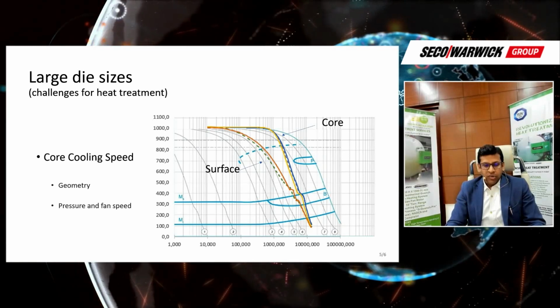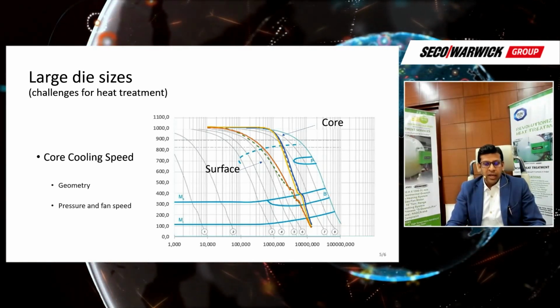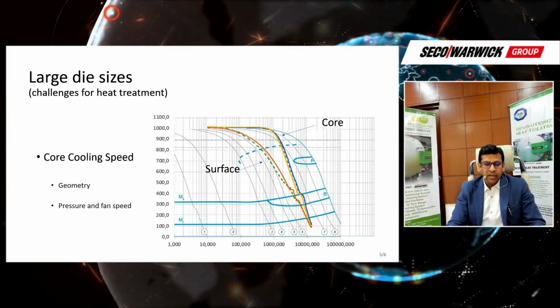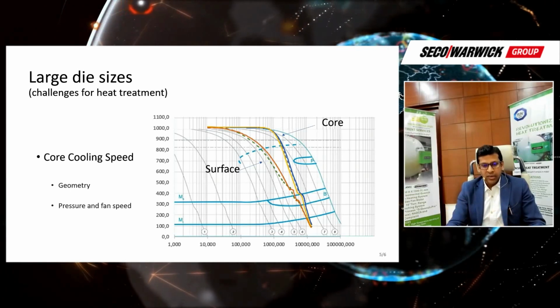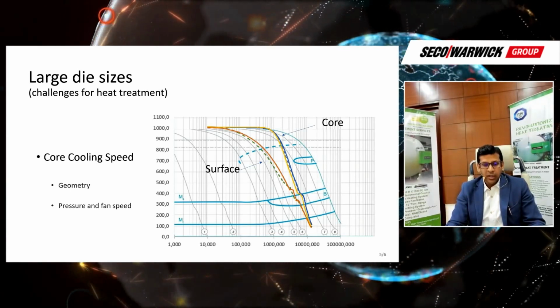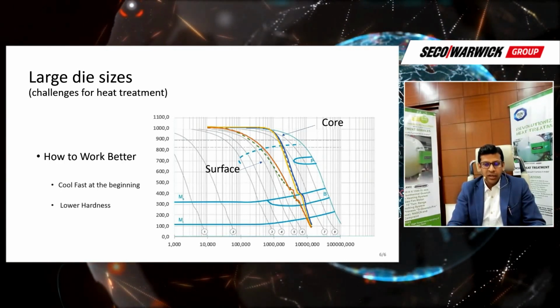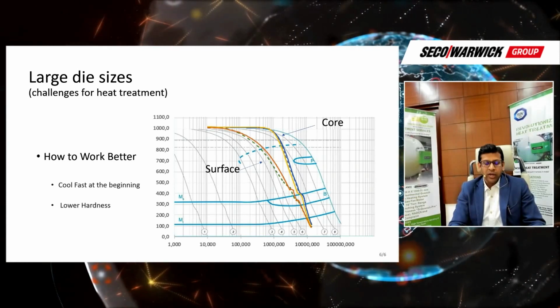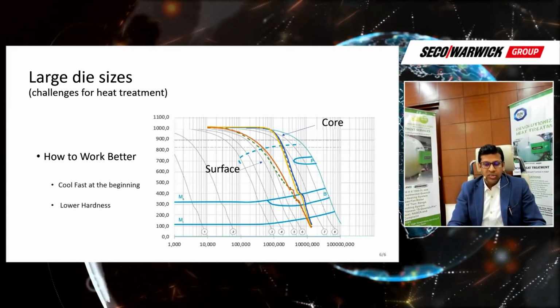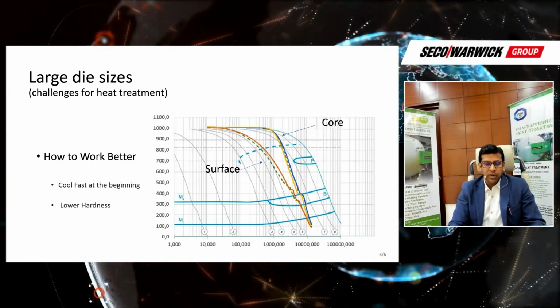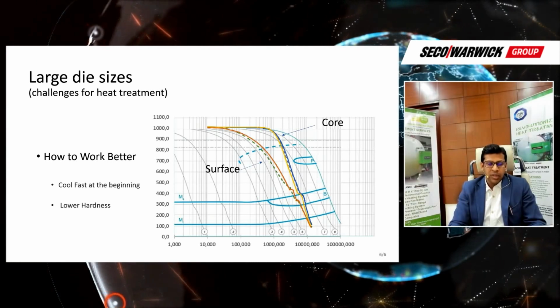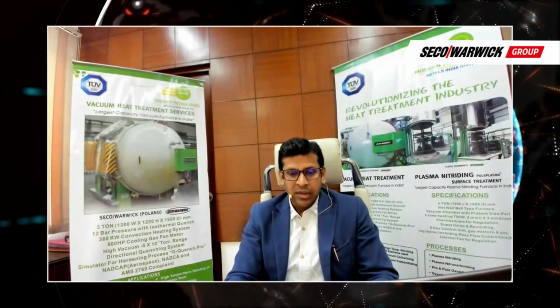Secondly, about the distortion, people are very much concerned, as Anita said, about the distortion. In bigger dies, yes, we have to have a very close discussion with the design team of the tool maker to leave some margin, or a good margin, for machining after vacuum heat treatment, so that we are able to have a good quenching rate as per the standards of the industry, maybe NADCA standards or tool and die industry standards, and to achieve a good microstructure with uniform hardness. But we have to compromise on the distortion at the same time. So this is a very big challenge during handling of large dies.